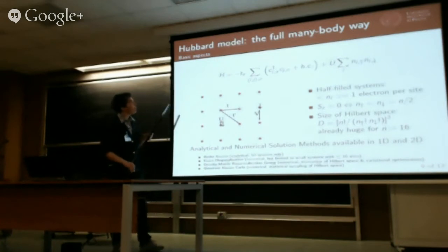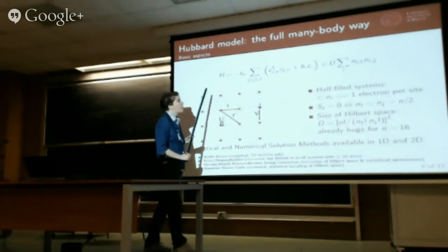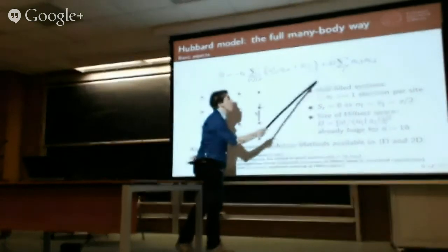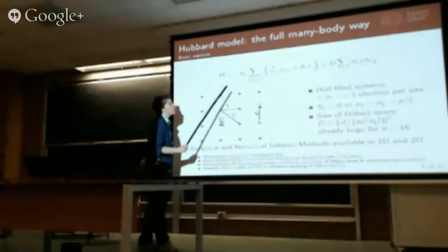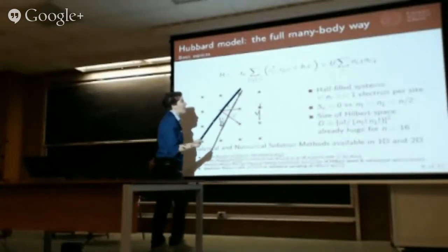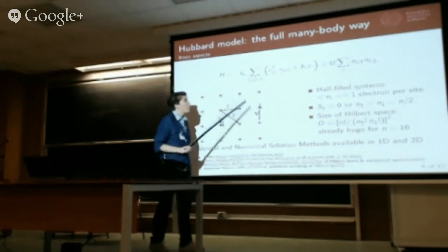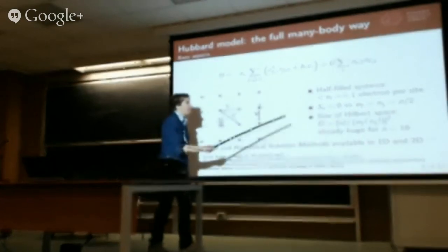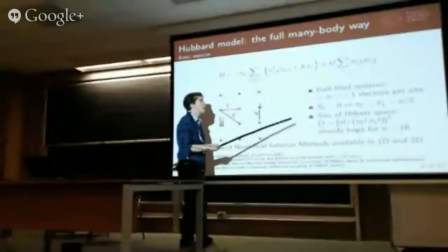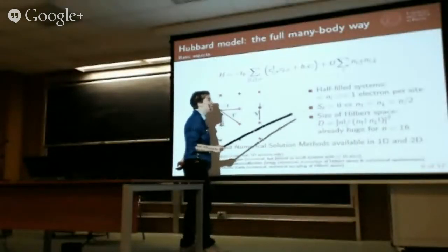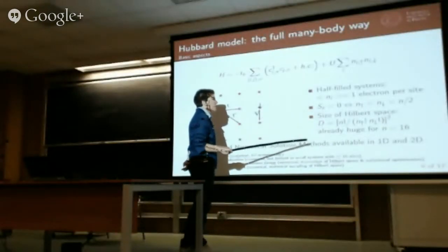For graphene nanoribbons, I've considered the simplest formulation of the Hubbard model, with just the U term for on-site Coulomb interaction added to the tight binding term, which was in the simplest case defined only for nearest neighbor hopping interactions. The basis set was defined for a half-filled system with on average 1 electron per site and 0 spin polarization.